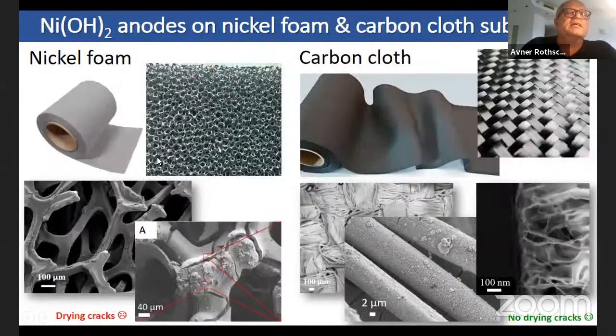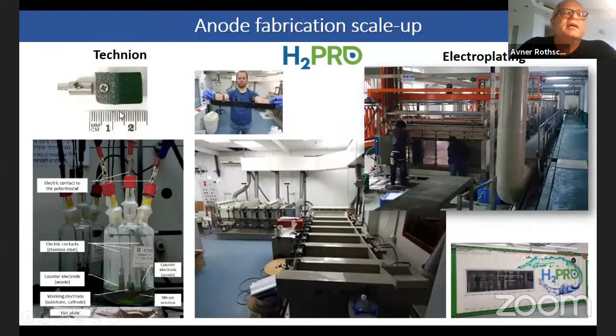So we started with nickel foam electrodes. Now we do this on carbon cloths that give us the flexibility and the potential to reduce the fabrication cost. We noted that on the carbon cloths, because of the flexibility, we get much less drying cracks, which means that the adhesion is much higher. And currently we explore this opportunity of working with carbon cloths. So in the lab, we generate these tiny electrodes. So 2 by 1 centimeter.